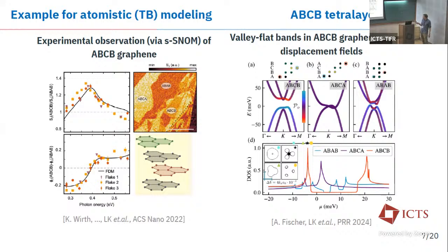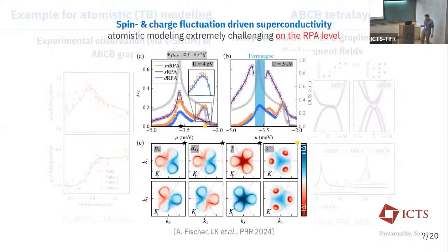The nice thing about ABCB graphene is that without an external displacement field, since you break inversion symmetry already on the crystal structural level, you have valley flat bands and van Hove singularities that are rather strong in the non-interacting band structure without any need of an external field. And we went through all the sweat and pain to do the atomistic modeling on the RPA level, which is extremely costly, as I tried to say before, and find how those local and non-local Coulomb interactions can lead to spin and charge fluctuation-driven superconductivity. So this is something like an RPA Kohn-Luttinger and combined theory. If you want any more details, I'm very happy to talk to you about this.